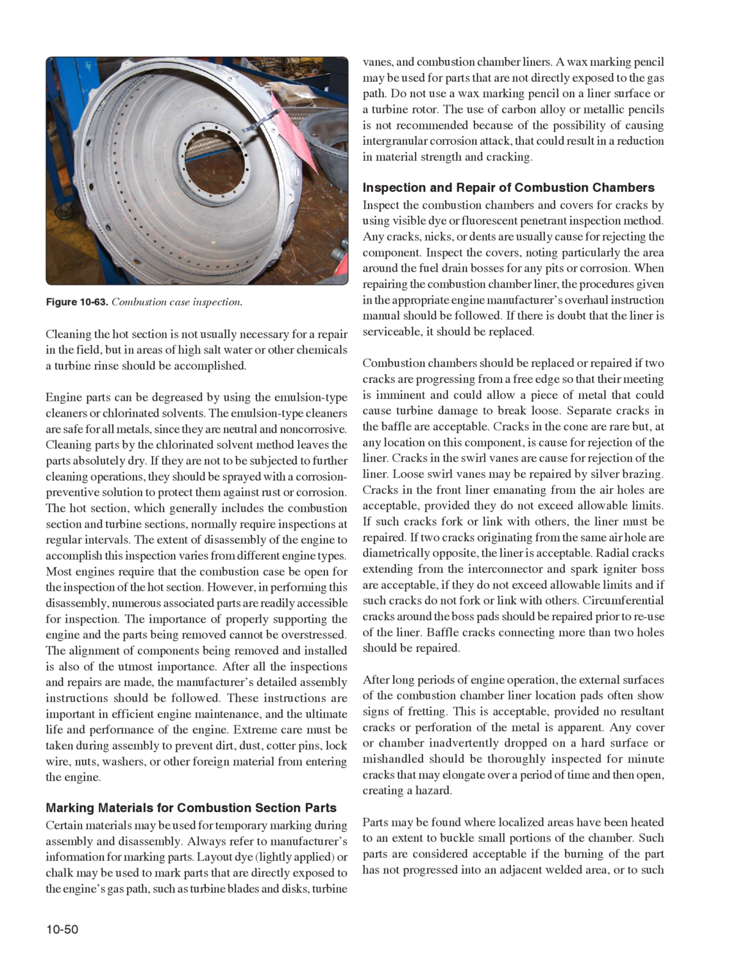The use of carbon alloy or metallic pencils is not recommended because of the possibility of causing intergranular corrosion attack that could result in a reduction in material strength and cracking. Inspection and repair of combustion chambers. Inspect the combustion chambers and covers for cracks by using visible dye or fluorescent penetrant inspection method.